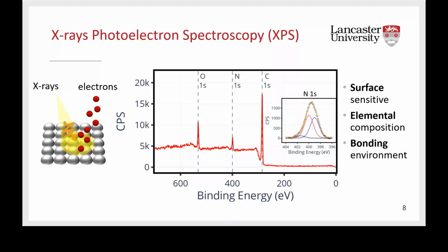Also, we can zoom in on a single peak, for example, the nitrogen 1s peak, to detect subtle changes in the energy of the electrons that are associated with bonding environments. However, XPS is confined just to the first 8 to 10 nanometers. However, we can mill through the surface: measure a layer, mill through the layer, measure the next layer, and so on, so that we can actually measure the chemistry of the whole sample as a function of the thickness.